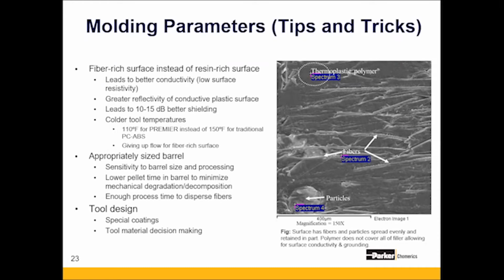So the material's melted correctly and it's had a chance to get mixed inside the injection unit. And the flip side to that is you can't hold the material forever, because like most polymers, if you start holding it longer than 5 minutes, you will degrade the material. So it's a little bit of a balancing act, but it's not difficult. This is the same kind of thing that people will do when they process time-sensitive materials like PBT.